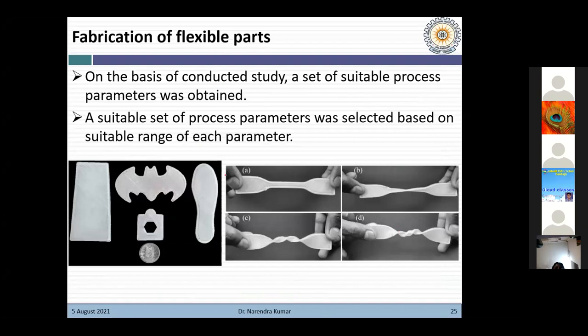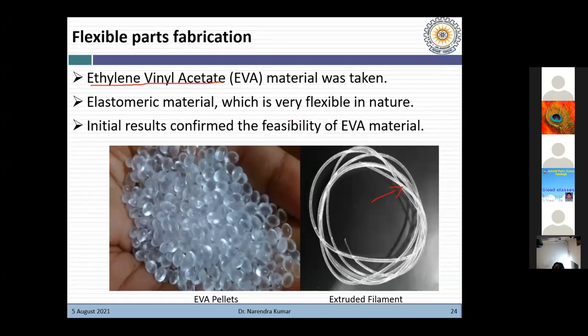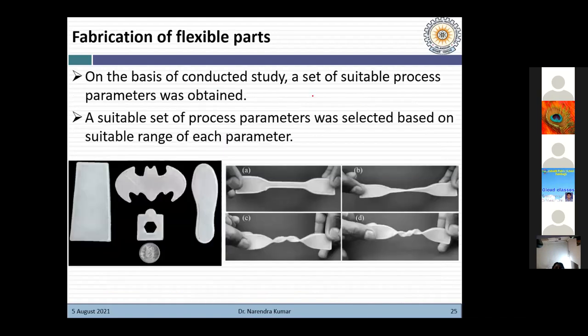Then we performed a parametric optimization. For this material, we optimized the temperature, the bed temperature, the screw speed, and the deposition speed. So various parameters were optimized by conducting the study. Statistical analysis was used to optimize the process parameters. Based on those results, a set of suitable parameters was obtained for this particular material, right? Because we found the range of the different process parameters, we then tried to print some of the parts.